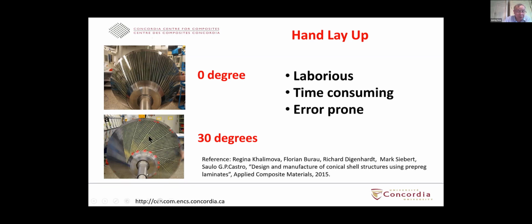Or if you want to make a fiber angle of 30 degrees, then again, you have to cut very complicated shaped strips to be able to do that. So this kind of technique certainly gives you a good structure in the sense that you can control the fiber orientation. You may have uniform thickness, but it is very laborious, it is time consuming, and also it is error prone. There was a publication in 2015 where they described this technique, but I could not find any result in terms of obtaining the axial buckling load. So basically the work had tried to develop some technique to make it by hand layup.